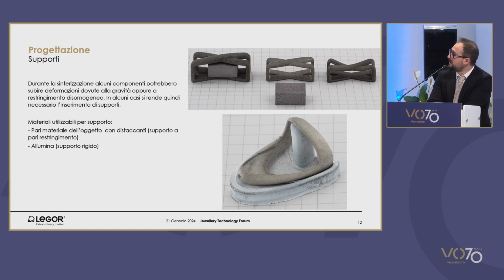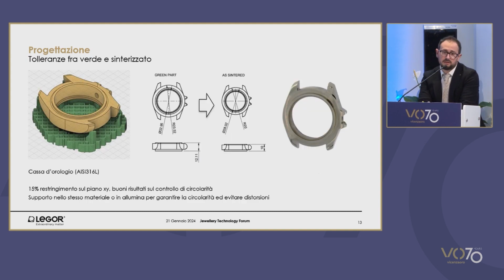In other cases, it is possible to co-produce both the item and the support. This has a meaning when we're talking about non-precious materials, but it becomes much more costly if you're using silver or other precious materials. Well, here the shrinkage phase that takes place during sintering allows me to have both the support and the item devoid of any tension that could take place when I have a base that has a certain friction, and therefore prevents the upper part of the item from sliding, causing tension at the base that could also lead to distortions. So these are two amongst the many tricks that allow you to obtain complex forms, bearing in mind the thermal phase of the alloy.